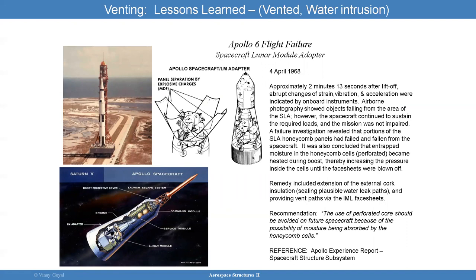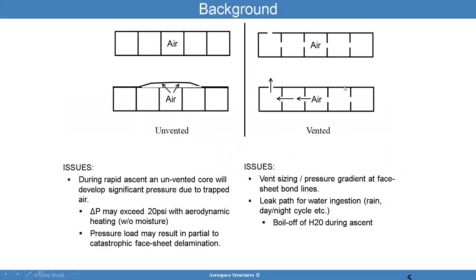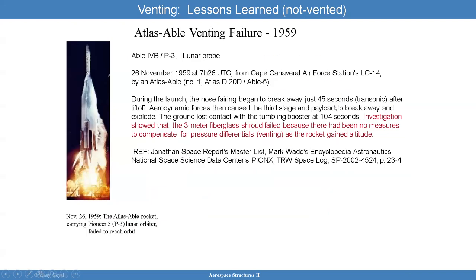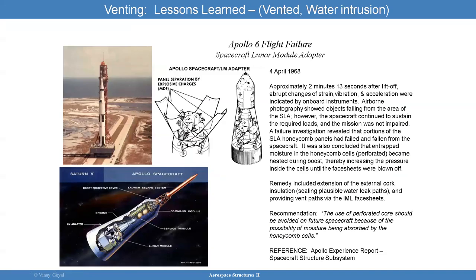We also have the Apollo 6 flight failure in 1968. In that scenario, the design was vented — more like the right-hand side schematically speaking — so venting was actually the issue. Why was it an issue? Because water ingressed, and the entrapped moisture in the honeycomb cells that were perforated became heated during boost. It boiled, and the pressure increased inside until the face sheets blew out.